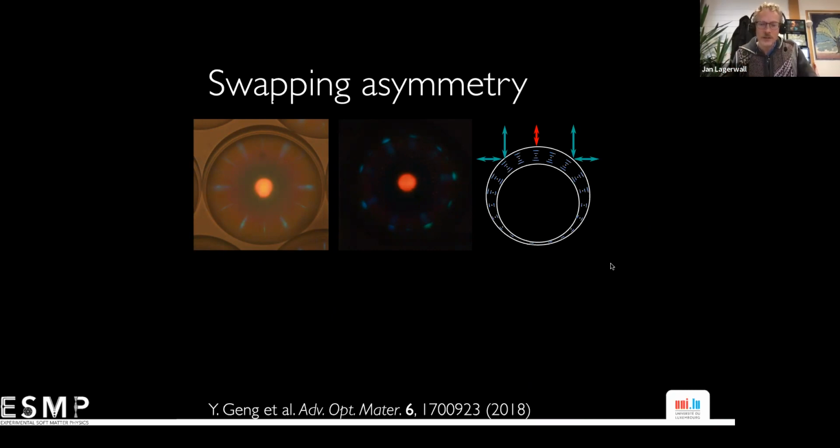But there is another aspect that is quite important, and that is that the asymmetry of the shell, as I mentioned in the beginning, also affects the optical properties. And I showed already that it affects the mechanical properties. But if you look at this shell here, from the side, it's thick at the top and thin at the bottom. If you look at it from the top, you get the pattern that we have been talking about so far, with the reflection in the middle, that's the retroreflection, and you have this communication pattern from the sides, that's communication with the neighboring shells.